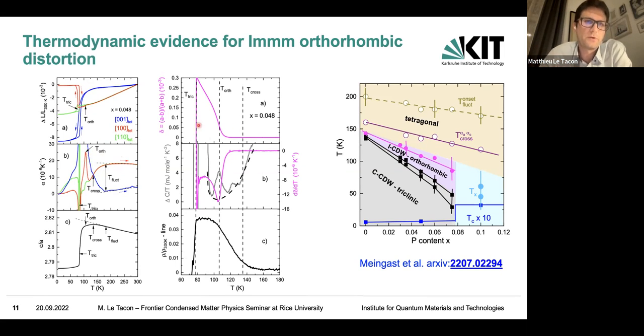And actually, from this measurement, you can directly extract the orthorhombic order parameter, and you see that its amplitude is of the order of 10 to the minus 4. To fix ideas, I'm going to show that a bit later, but that's at least an order of magnitude smaller than what you have in the iron-based system. Now, what's nice in that study is that you also have specific heat data, and you can see that there is a peak in the specific heat. It's a very tiny peak, which is associated with this orthorhombic distortion. So you can really see that it's an actual phase here.